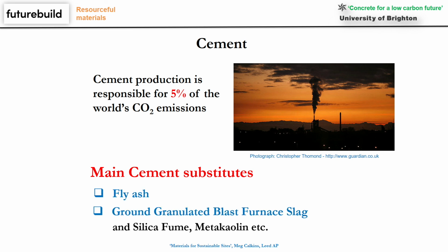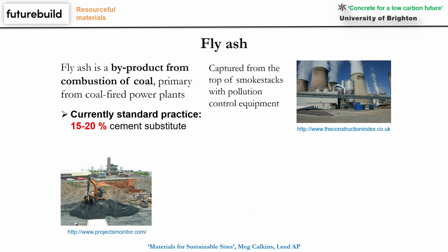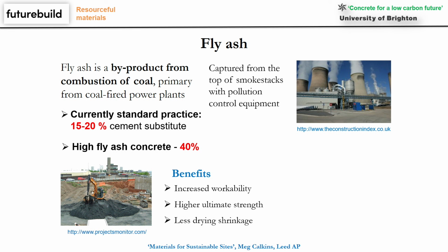At the moment, we are using as cement substitutes fly ash, GGBS. Some of the previous speakers talked about this. And we use other materials as well: limestone, metakaolin, silica fume, and so on. Fly ash, probably you know what it is. It's a byproduct from the combustion of coal. This is what we collect from the chimneys of the coal-fired power plants. It's a waste product, and current practice is something like 15-20% replacement of cement, or it can go up to 40% in very high fly ash concretes. We have some benefits such as increased workability, higher strength, less shrinkage, and we have some drawbacks too, so we can have some longer setting times, which can be detrimental for the early age strength of concrete. So we need to be careful when we are using these materials and at which percentage we can use them.